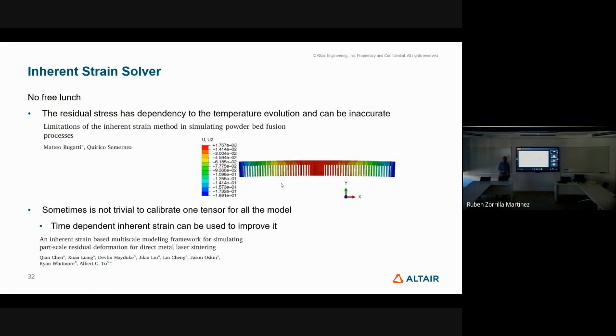But there is no free lunch. In fact, the residual stresses may depend highly on the temperature evolution. There are papers claiming that they do this sign, and this sign usually goes up, so your inherent strain is usually negative. But in some configurations, it goes down, which is the complete opposite. So this calibration may give you a wrong result. In practice, it's very difficult to get that situation, but at least if it exists, it means that there are limitations.